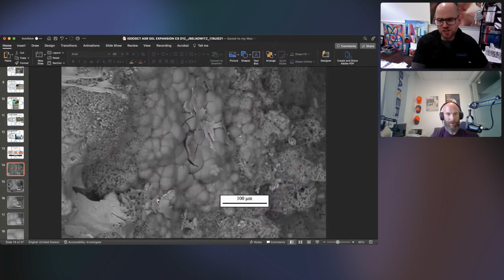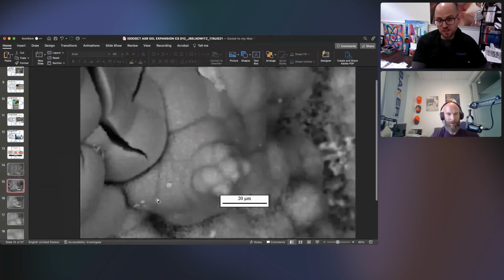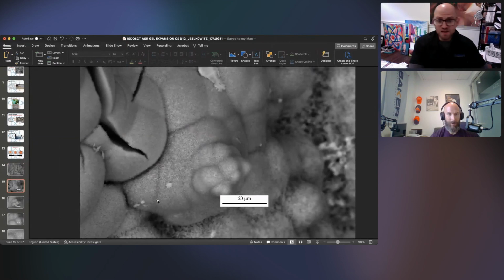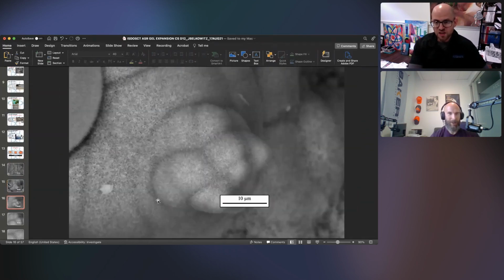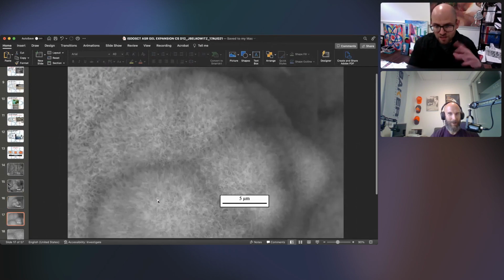This is an ASR gel rosette, and this is under a scanning electron microscope. And I'm going to zoom into it because as nasty as it is, the beauty of this is where the destructive nature lies. Like it's something from a zombie apocalypse movie. Looks like a wart. As we get closer into it, it goes from this bubbly rosette to where you can start seeing this fibril, wispy-like morphology.